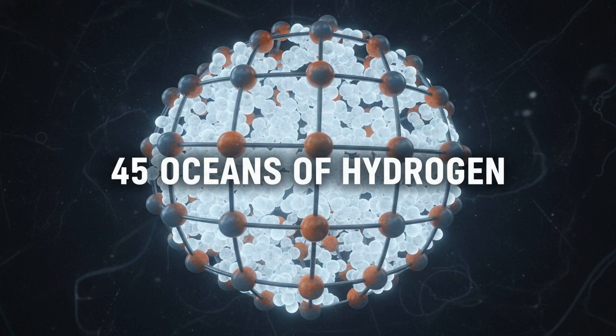By taking this 1-to-1 hydrogen-to-silicon ratio and combining it with highly established geophysical estimates of the amount of silicon present in the core, the researchers calculated the total mass of deep Earth hydrogen. They concluded that hydrogen makes up roughly 0.07% to 0.7% of the core's total weight. While a fraction of a percent might sound insignificant, the sheer mass of the Earth's core is almost incomprehensible. When translated into volume, this tiny percentage equates to an astronomical amount of hydrogen.